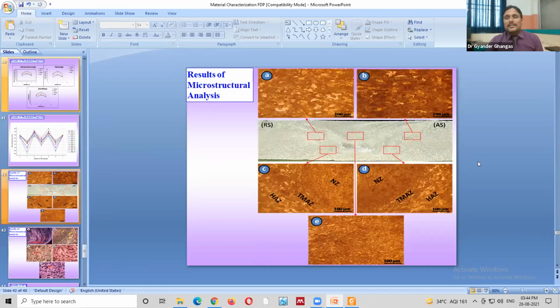For microstructure, one specimen was analyzed, and this is the specimen. There is the nugget zone, TMAZ, and HAZ on the retreating side and advancing side as well. So the difference between the grain sizes or shapes in all the different zones can be compared easily, because this is the HAZ of the retreating side, this is the HAZ on the advancing side, this is the nugget zone with finer equiaxed grains, and these are the TMAZs. Here we can see some elongated grains just because of the application of mechanical force by the tool pin.